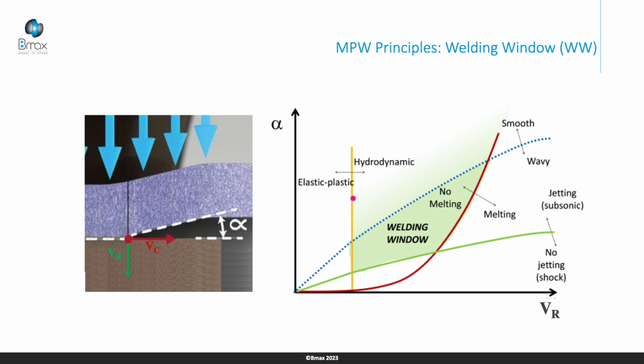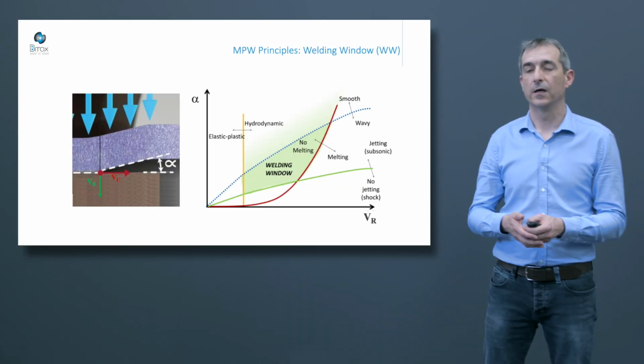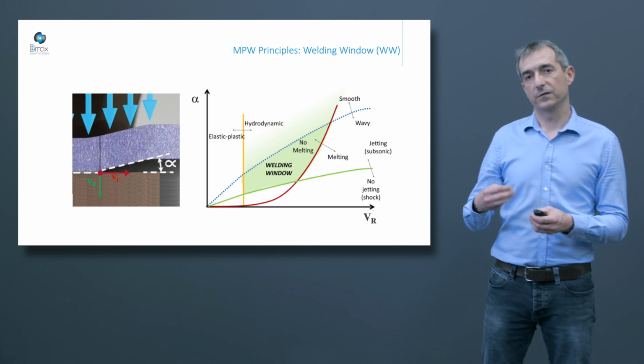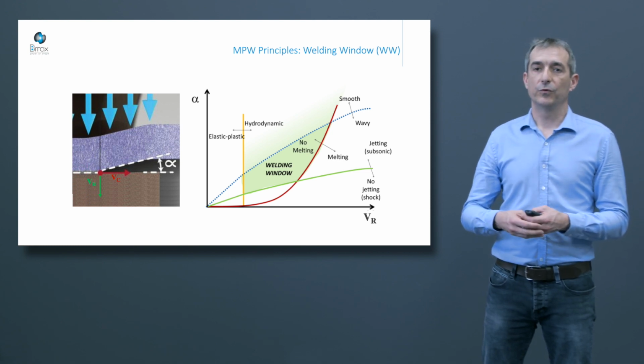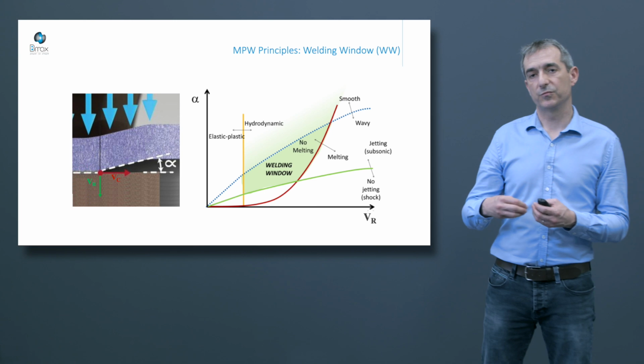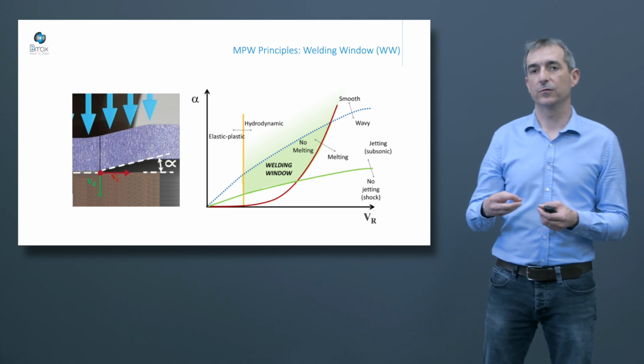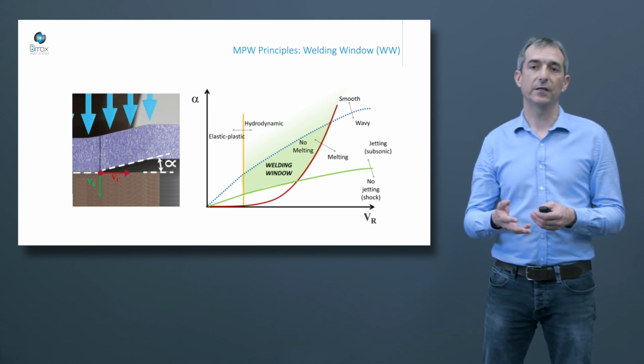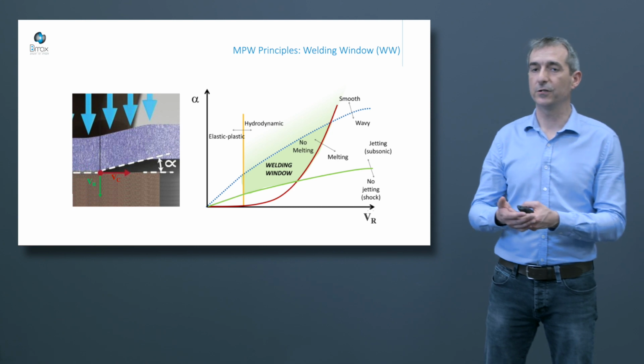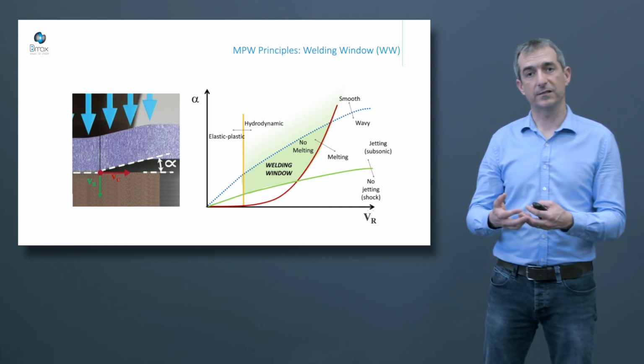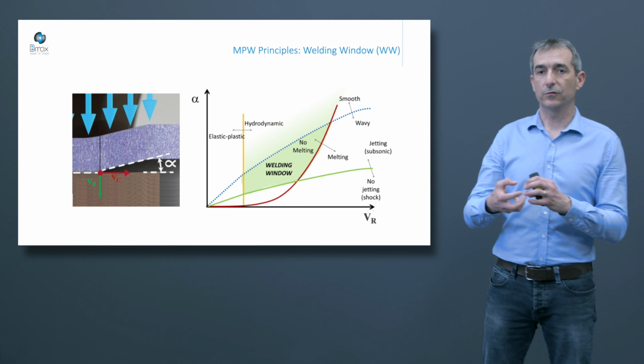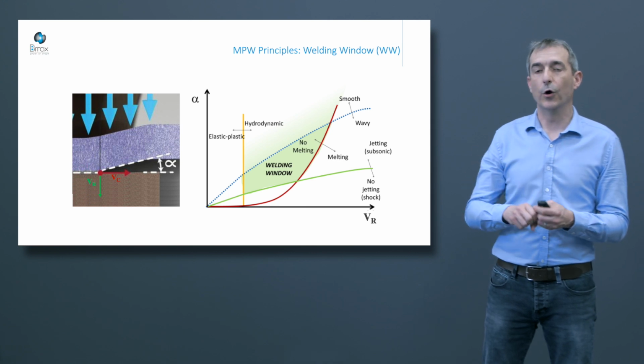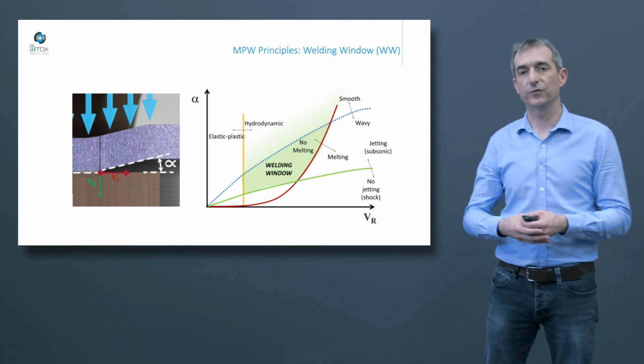The first limit is the yellow straight line. We have to reach high speed to activate hydrodynamic behavior in the material. After this limit, when we reach this speed, we create high pressure, and this pressure is predominant, and the material is like a fluid. Thermodynamically, in terms of pressure and temperature, it's in the solid state. But the hydrodynamic behavior means a fluid behavior. So it's the first limit of the welding window.